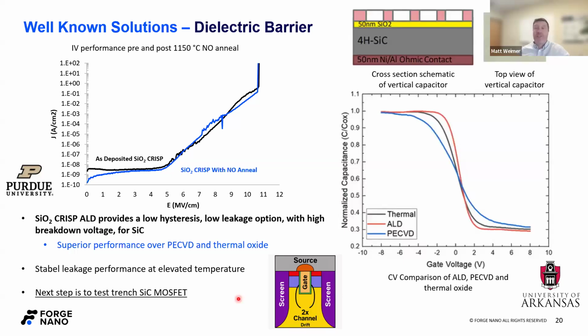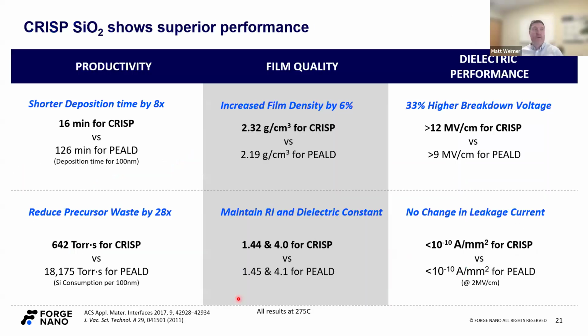Of course, we can maybe have a broader discussion about whether the transition to trench will happen or if people just want to stay planar. But I think it's our perspective that some part of the market will transition to trench, and that it will require a high quality ALD silicon oxide dielectric. Okay, so I promised some film properties for the silica crisp. I always like to compare it to a PEALD film, a plasma enhanced ALD film, because that's really what you see for silica in the market. Most thermal silica films are quite low quality. So this was pulled from a couple of different papers using a very similar precursor at a similar temperature.